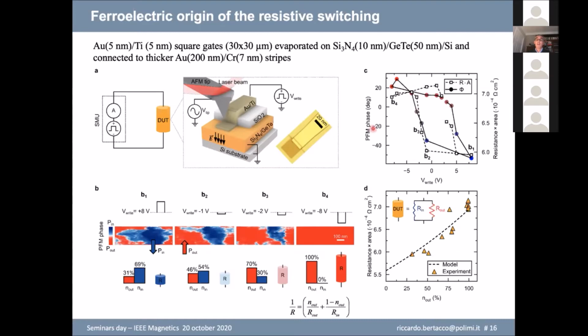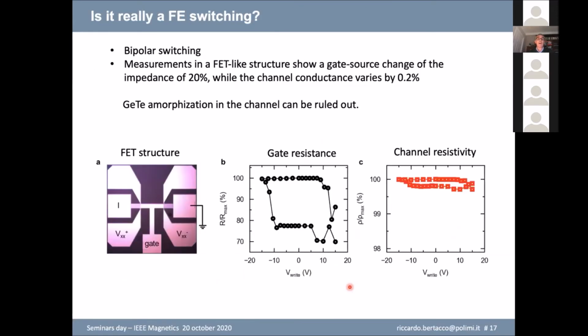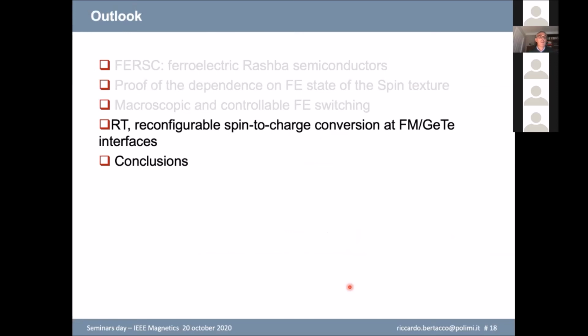When you look at the PFM phase, you have with continuous line, this hysteresis loop, which is superposed to the resistance loop, which means that really the resistance change is following the ferroelectric states. And you can also model the resistance change using a parallel resistor, a very simple model. Okay, that's a very important demonstration that we are really looking by an IV measurement to the ferroelectric states. I will skip this aspect here.